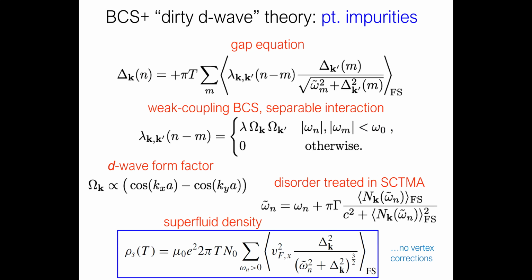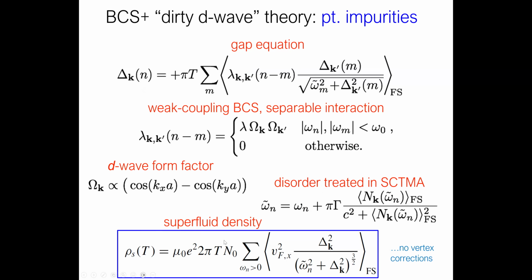Okay, so the equations are fairly simple and well known. It sometimes goes under the name of dirty D-wave theory. You have a BCS-like self-consistency equation, a gap equation. You assume a separable interaction with D-wave form. And then you have some equations for the disorder self-energy with the impurity phase shift built in here. And this is an average of the Green's function over the Fermi surface, essentially. Let me go back. Sorry, I didn't quite get to the superfluid density. This is the BCS expression for the superfluid density, this famous 3/2 function of Matsubara frequencies.